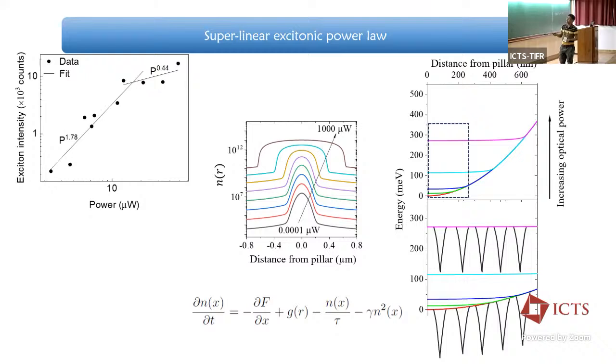However, you don't see this blue shift, because as I told you, there is this electron doping, which is red shifting and just cancelling it. But nonetheless, the pillar diameter is actually increasing, and so you are covering more and more Moire pockets. It is an area, right? It will go as a square, and that's why this close to 2 is coming.